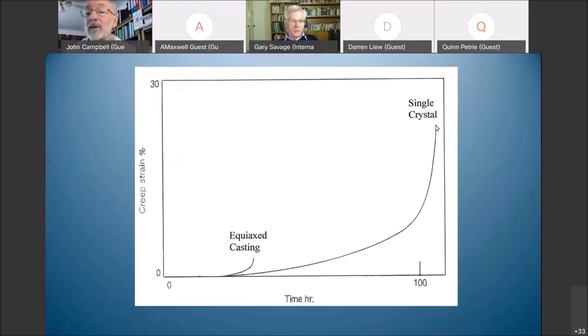And that's interesting because it tells me that there are still some bifilms in there, and the single crystal process didn't get rid of them all. Nearly all, but not quite. Still enough to cause it finally to fail. See, if we'd been successful to get all of the bifilms out, the answer is it would never fail by fracture. It would keep on extending and extending and getting thinner and thinner, and would finally come apart at the last atom, but it should never fracture. Okay, so you can see there's terrific potential for affecting the creep of metals.